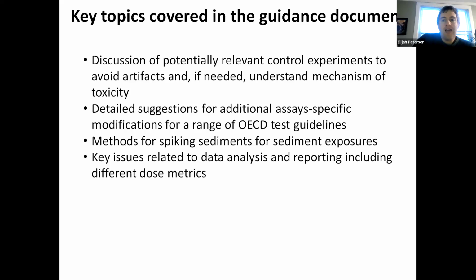There was assay-specific guidance for a range of the methods, where we provide general guidance and then hone in on a specific method or two, or a method by itself, and describe some of the challenges there. And as I was saying in the previous slide, there are some things about dose metrics and what we suggested. We suggested using mass-based concentration since that's the most widely developed for standards. Hopefully in the future, we'll have methods related to nanoparticle number concentration, but we're not there yet. We also discuss sediment testing and some of the nuances related to that.